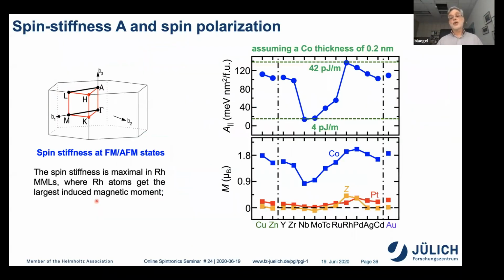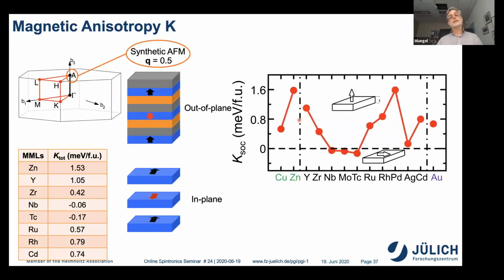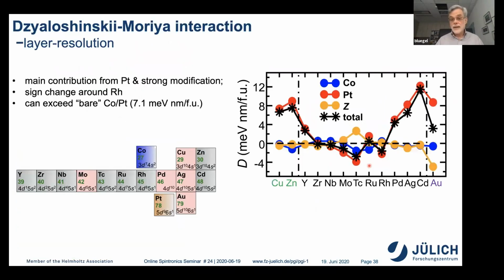And with the cobalt moment scales the spin stiffness. The strongest spin stiffness we have for rhodium, isoelectronic to cobalt. And we get also the magnetic anisotropy. You see the magnetic anisotropy of cobalt is largest at the beginning and the end of the transition metal series. The largest one is for palladium. For niobium, molybdenum, technetium, it's in plane. Okay, then technetium is not so relevant.